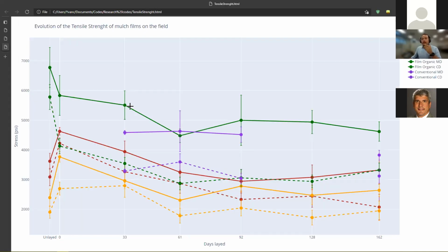Finally, we also get from mechanical testing the tensile strength. That is a continuous measurement. We can get it all the time, and there's a clear trend of going downwards to lower values from the initial tensile strength of the material. So that can maybe be used as a good indicator for biodegradability.